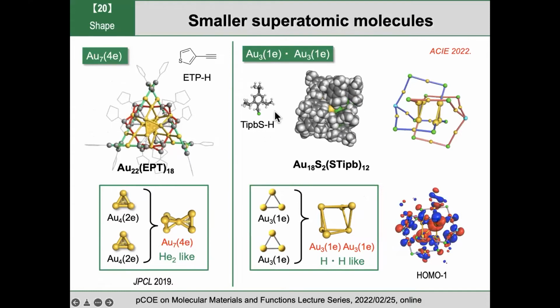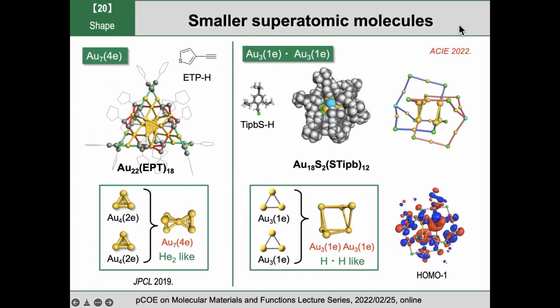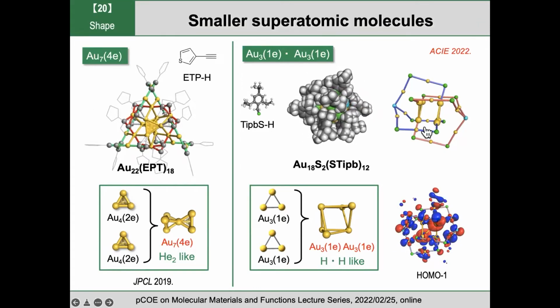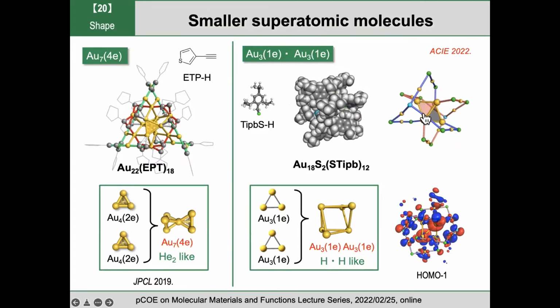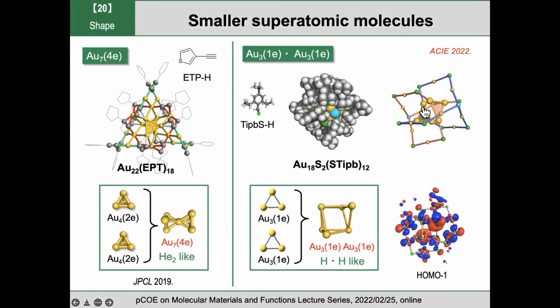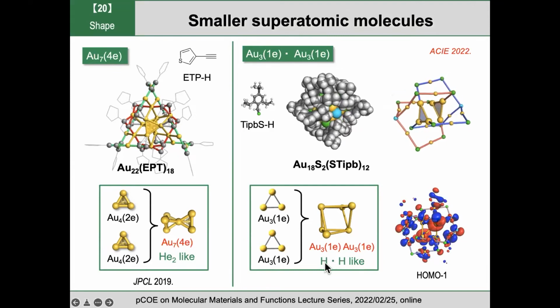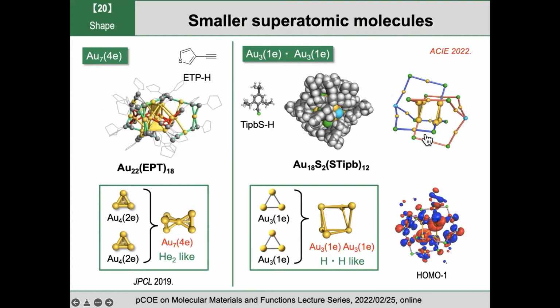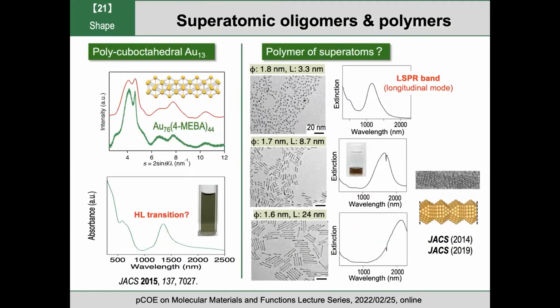When we use this bulky thiol, we have these structures. And the core of this cluster is composed of a pair of gold trimers, you can see. And the electronic structure of the core corresponds to very weakly bound hydrogen atoms, okay? Because there is actually no bonding between these two atoms. And the trimer pairs are weakly bound, supported by this framework. Okay, so this is another example of the superatomic molecules.